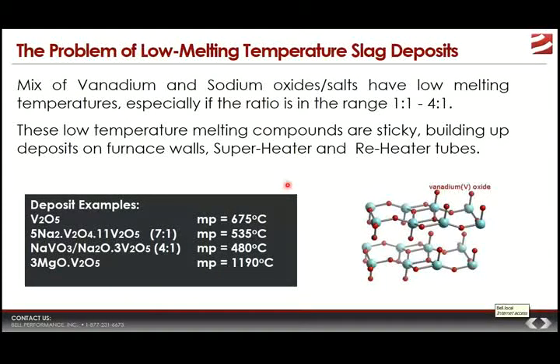Some problems for HFO users arise in part when they get these low melting point deposits formed. When the fuel has the wrong mix of vanadium and sodium, it can form deposits that have a metallic composition such that the melting points of those deposits are pretty low. Here you can see some examples. A deposit that is just V2O5 has a melting point of around 675 degrees centigrade. When you start adding sodium into it, such as when you have a 7-to-1 ratio here, you get an even lower melting point, 535. When you have this kind of deposit, the melting point's even lower, 480 degrees.